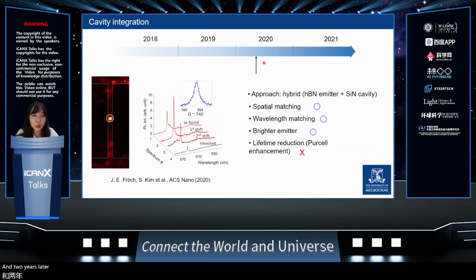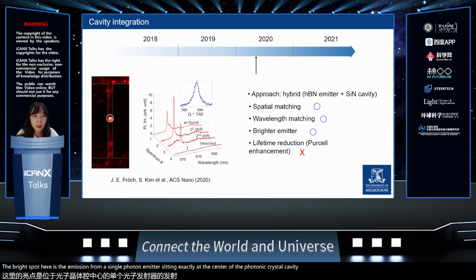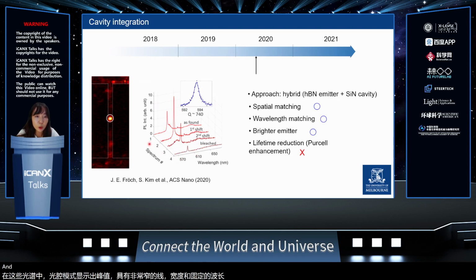Two years later, in 2020, we were finally able to couple emitters to the cavity mode. The bright spot here is the emission from a single photon emitter sitting exactly at the center of the photonic crystal cavity. In this work, we are in the bad emitter regime, which means that the quantum emitter has a broader linewidth than the cavity. In these spectra, the optical cavity mode shows a peak with a very narrow linewidth and a fixed wavelength. Still, tuning and detuning the emitter wavelengths to the cavity resonance is necessary. In this work, we tracked the spectrally jumping emitter, which allowed us to observe the intensity enhancement, as shown in the second graph.